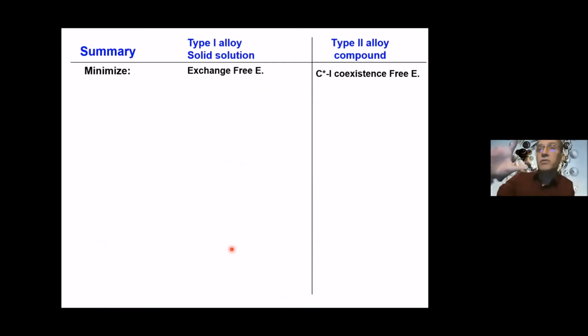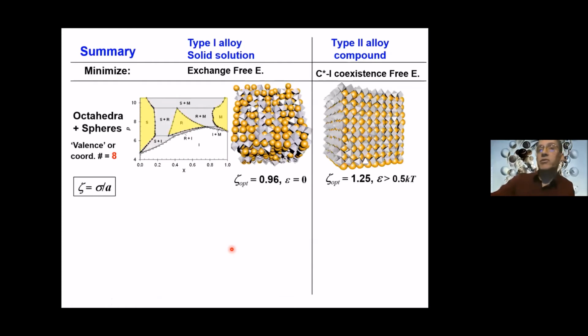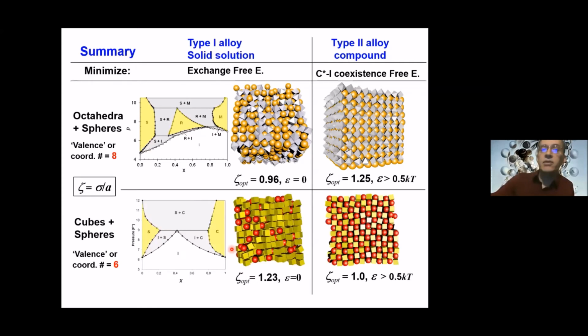So for these 2 types of alloys, we've identified, we postulate, these general free energy quantities that would be the metrics to optimize that behavior. I've shown you results for this test bed. I didn't show you results for this other test bed of cubes plus spheres. One key difference is that in some ways the valence or the coordination number of the lattices changes from being 8 here to being 6 when you use cubes. But the main conclusions are the same.